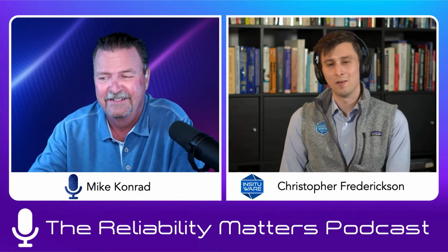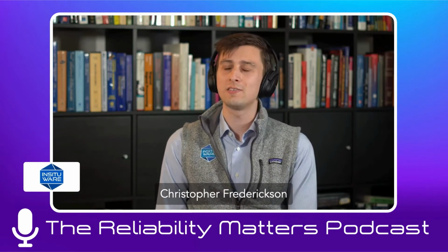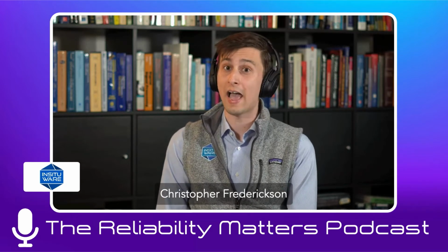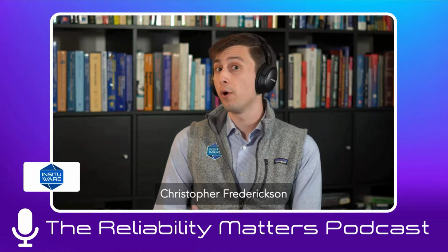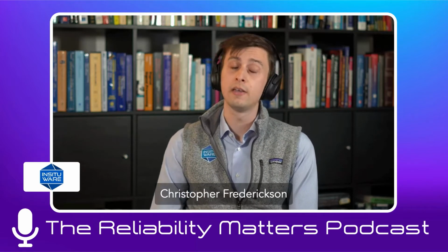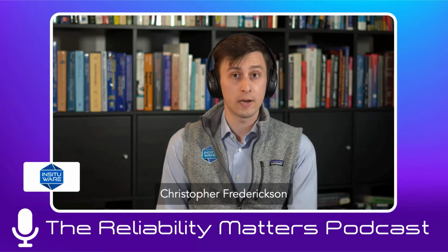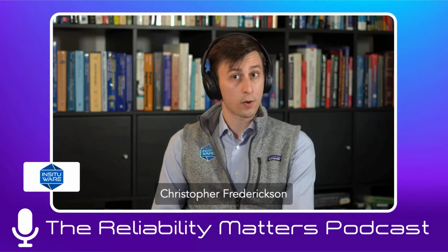Yeah, the best preventative measures that you can take are the ones that I think are already well publicized and known. The manufacturer's guidelines are quite accurate when it comes to handling solder paste, where you want to ensure that it's never heated up. You want to ensure it's kept at room temperature. Don't open the solder paste cold. You stir it to homogenize it well. If you follow to the T everything that the solder paste manufacturers recommend, in a lot of cases it will perform quite well.